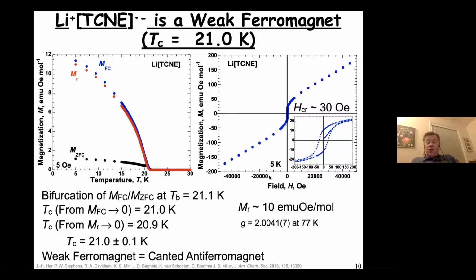In either case, you can use the remnant magnetization and the expectation, if it was fully magnetized at 5585 EMU Oersteds per mole, and calculate through this equation the canting angle for this canted anti-ferromagnet, weak ferromagnet. And that canting angle is actually very small, approximately 0.5 degrees. So we've characterized this material as being a weak ferromagnet ordering around 21 Kelvin.